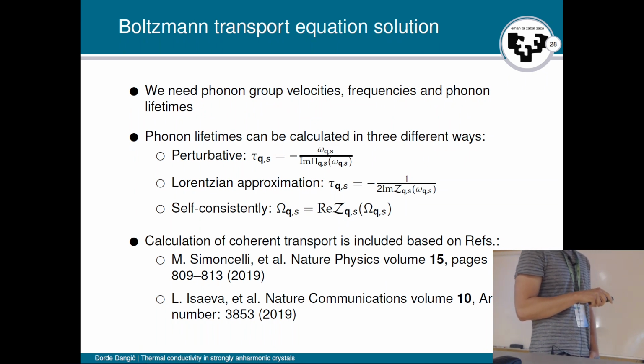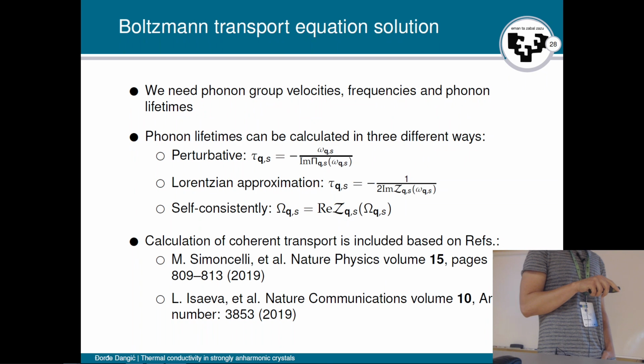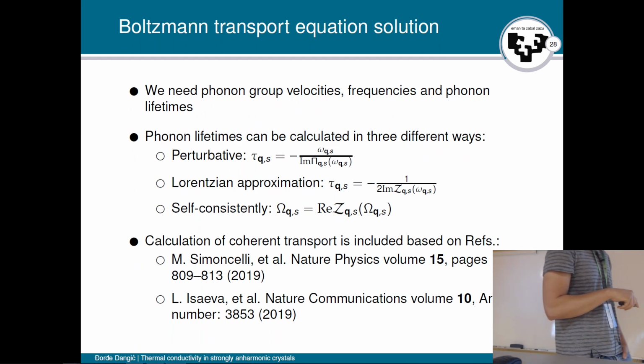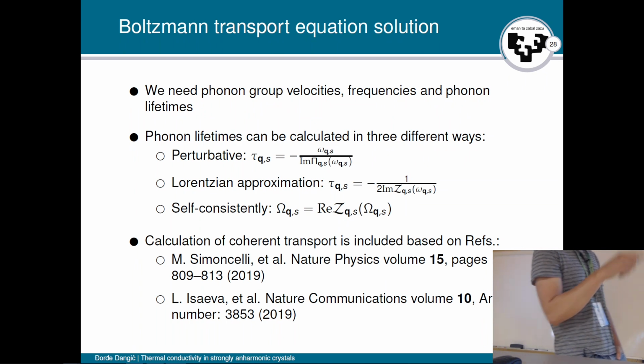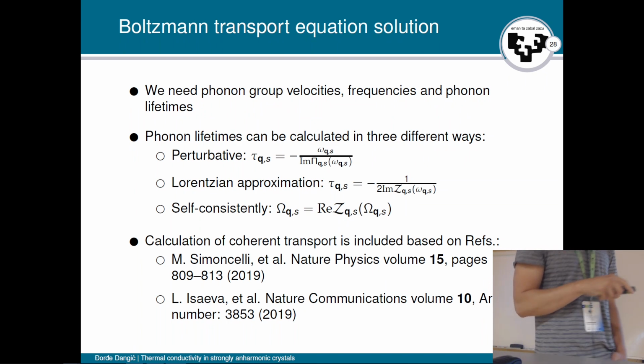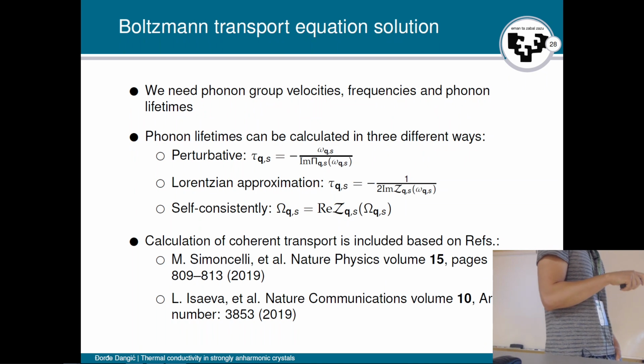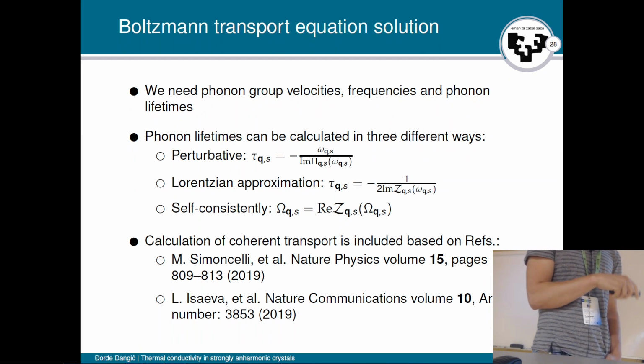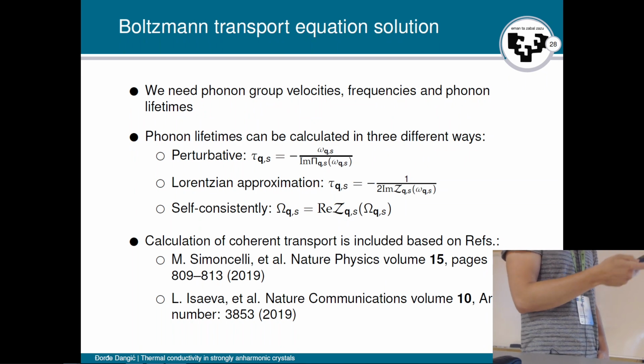Another way of getting the phonon lifetimes is to solve this equation self-consistently and then calculate the phonon lifetimes not at the SSCHA auxiliary frequency, but at the self-consistent solution of this equation. And also, you can calculate this coherent transport, or whatever you want to call it, the one that's important for amorphous materials and complex crystals, based on these 2 different approaches, which should give similar results. It is actually interesting that these 2 results are different from each other, and they also differ from the Green-Kubo approach. So, yeah.